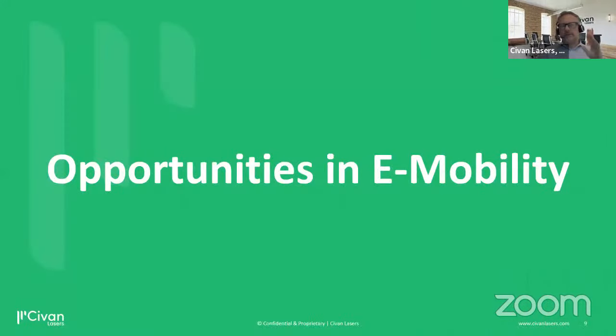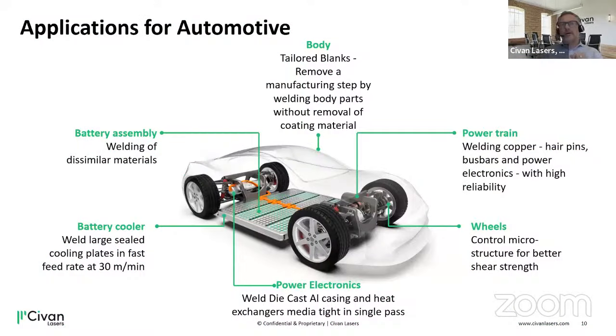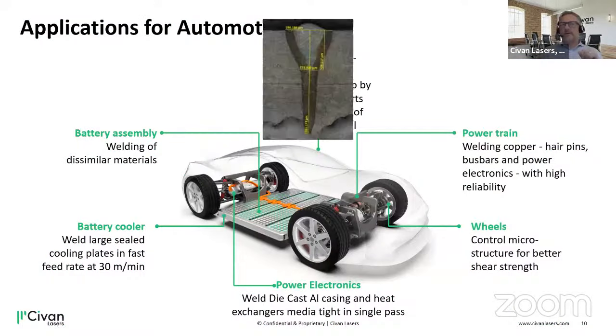But since we mentioned this as opportunities in e-mobility, well, it starts with the blank sheet of metal. If you have applications like coated steel, for instance, tailored blanks for hot formed parts, you can weld them directly without grinding down the aluminum silicon coating. Obviously, this is not the result you want, but typically what you want is the opposite. You want to have a totally homogeneous mixture, but then you won't see anything. So this is our proof that we have control over the weld.